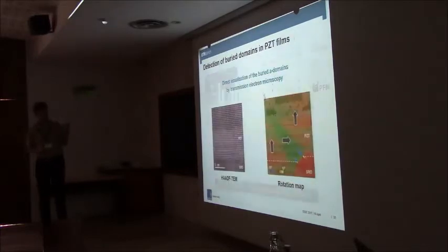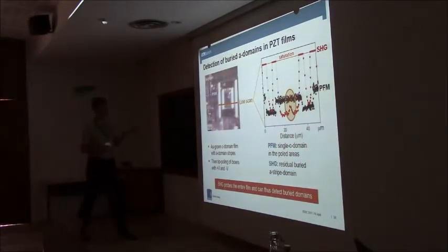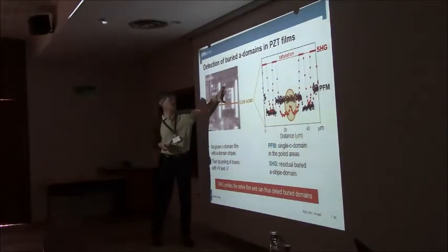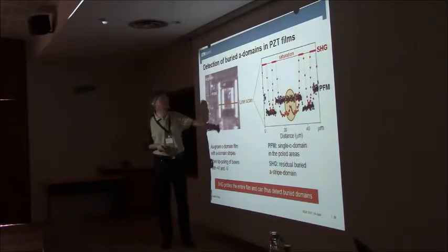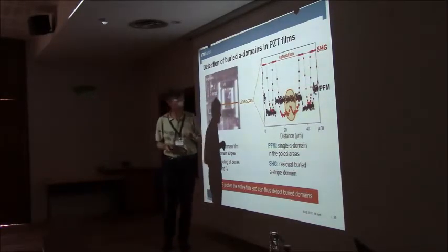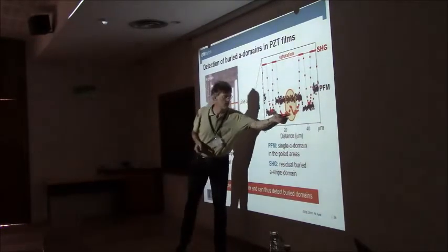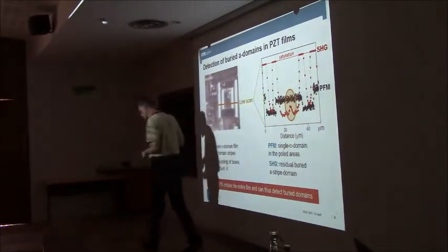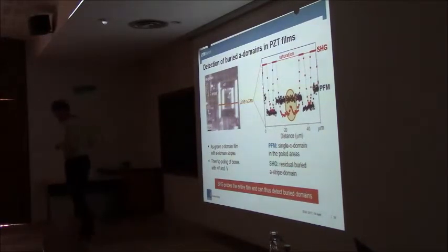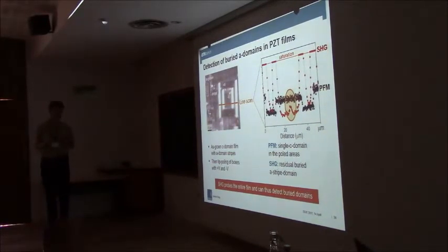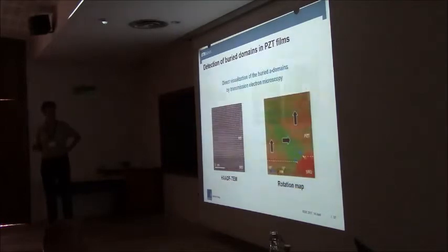That's exactly what then puzzles a company. So they think we have polarized it, it's all nice, all C domain, we can work with it, technologically great, but somehow it doesn't work. Why not? Because they don't see that there is a domain at the bottom that interferes with the domain movement as they want to have it.